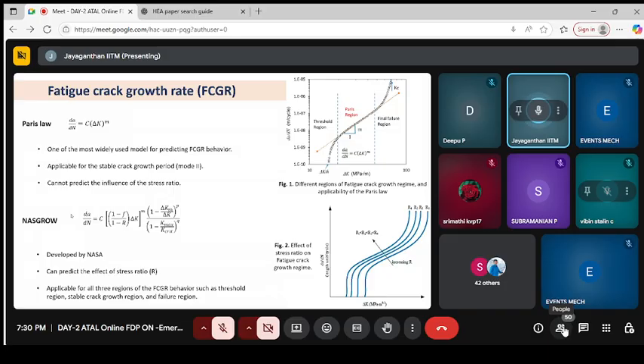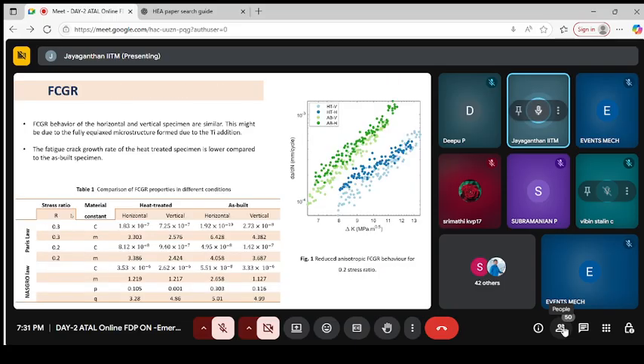So the middle region can be captured accurately by using Paris law. For the non-linear regions at the beginning and at the end, Paris law does not apply. And NASGRO, once again a model developed by NASA, can account for the influence of stress ratio much more accurately. That is where, right from the beginning to the end, it is able to capture the rate at which the crack is growing in a given sample. We analyzed the estimated data through this NASGRO model. And to compare the heat-treated sample and the as-built sample, we applied both Paris law and NASGRO. NASGRO is able to predict the rate at which the crack is growing.